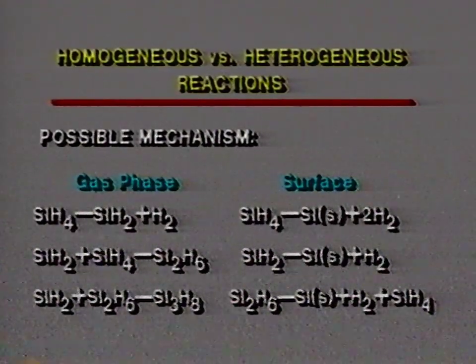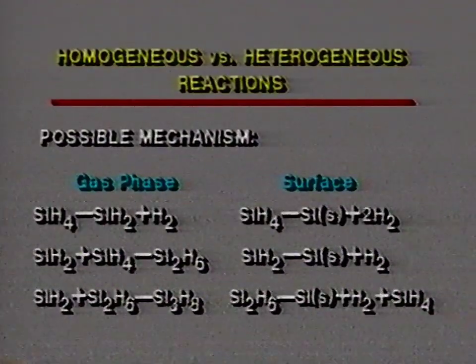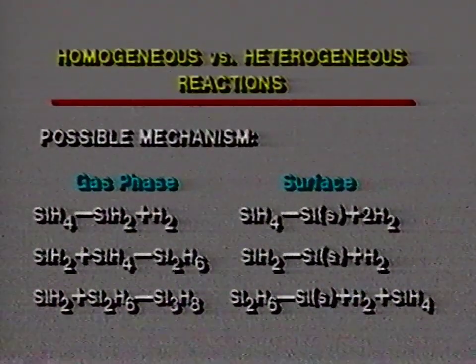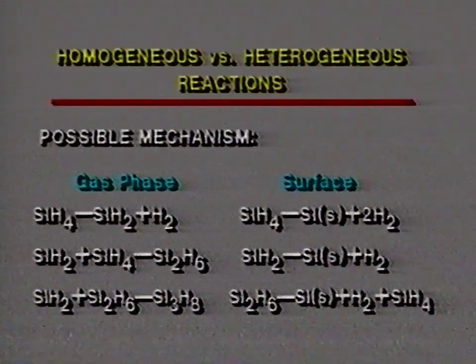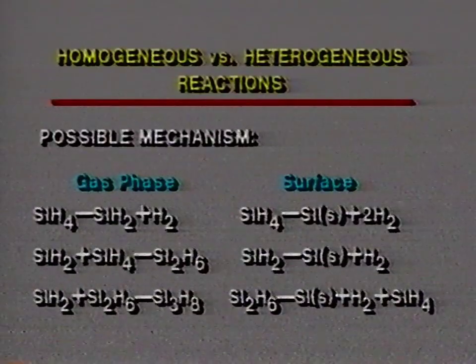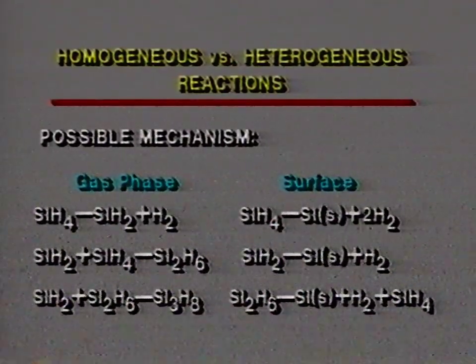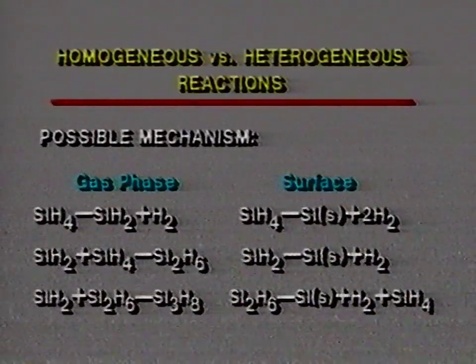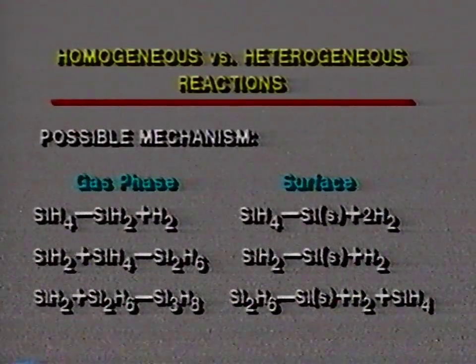Now, all of these reactions occur in the gas phase, and there are many more intermediate steps. On the surface, on the other hand, we have silane depositing directly as silicon, elemental silicon and hydrogen, in all cases, whether it is silane or disilane or the more complex type. So these are the types of reactions, of course, which we would like to have, namely the deposition of film on the surface. Incidentally, of course, in all of this, we are really concerned with the deposition of thin films rather than anything else. And thin films meaning films in the range of a few hundred to a few thousand angstroms up to perhaps a micron or so for VLSI type applications.